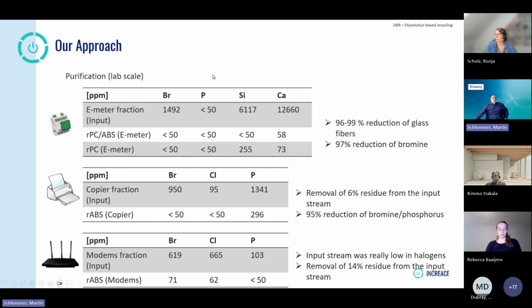With respect to purification, let's look into some typical elements in that feedstock, which is on the one hand the bromine, which comes from brominated flame retardants. We have phosphorus coming from phosphorus-based flame retardants. We have silica and calcium coming from typical inorganic fillers. And you see here that in the feedstocks, it is sometimes a bit higher brominated, no phosphorus in, but we still have higher filler contents. This is somewhere in between, and you see the Modems fraction is quite the purest in a way. In these two cases, we have some values of chlorine measured coming from any feedstock in that range, not directly identifiable. In the end, you see that the products we got out are really far lower than the feedstock.